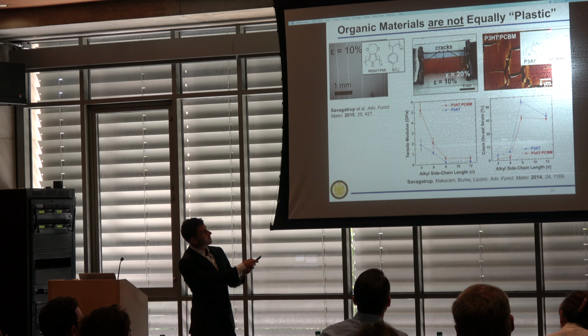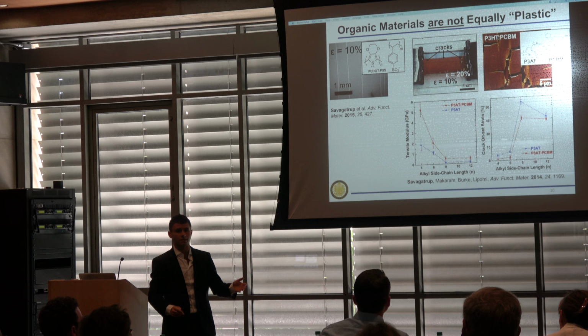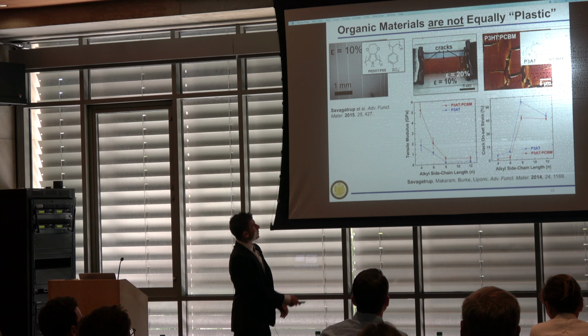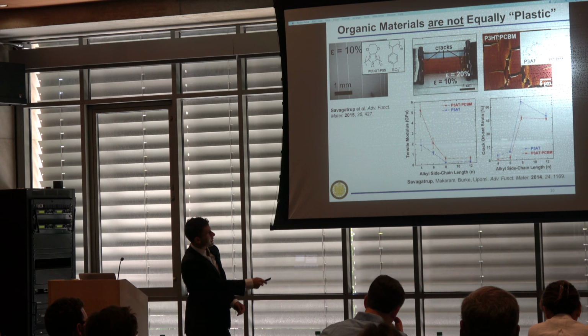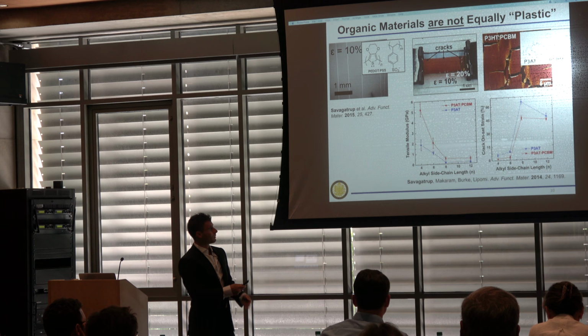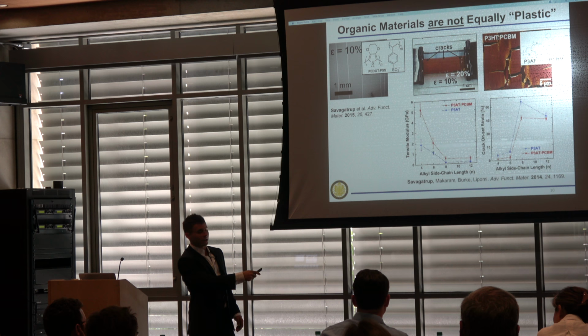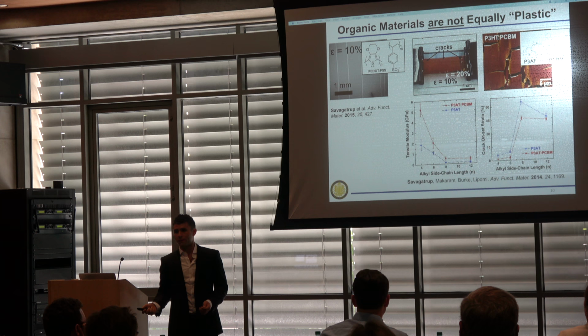I'll refer to these by carbon chain length: if it has a carbon chain length of 6, I'll call it C6, and a carbon chain length of 8, I'll call it C8, and so on. As you increase the length of the carbon chain, you decrease the tensile modulus, and at about C8 this effect plateaus. Conversely, C4 and C6 crack at less than 5% strain, especially in a composite, around 3%. And then at C8, all of a sudden you can stretch your device up to 45% strain.